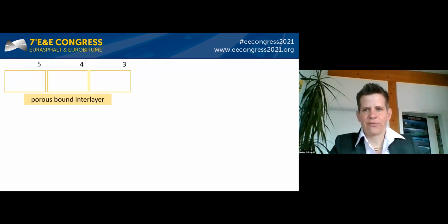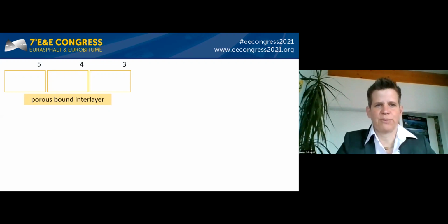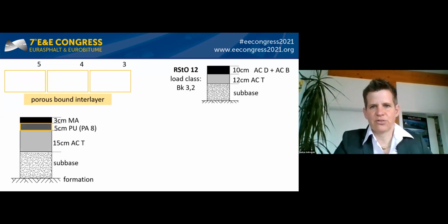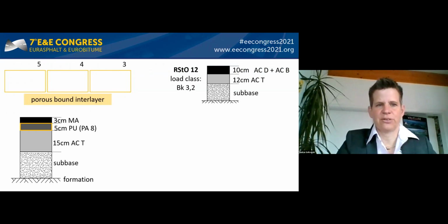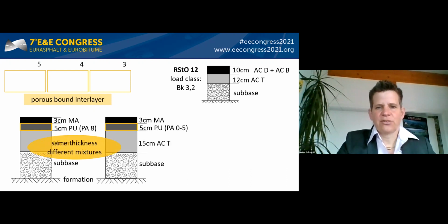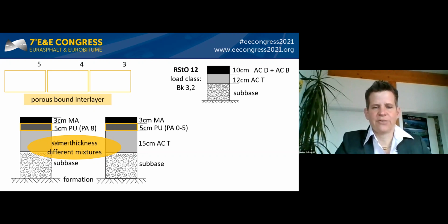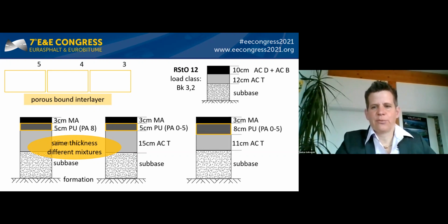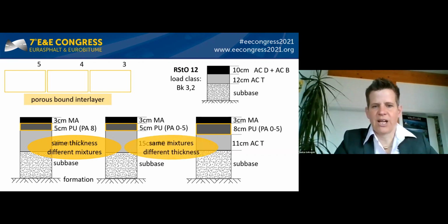So we will have 3 different sections with porous bound interlayers. They are also referenced to our standard. And we will have a 5 centimeter interlayer with a gradation of 0 to 8 millimeters grain size. The second section will have the same thickness, but we will use another mixture, another gradation. And the third section, there we want to use the same gradation of the mixture, but we will have another thickness of the pavement.